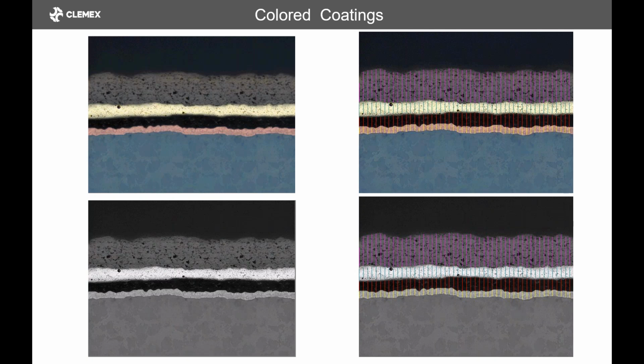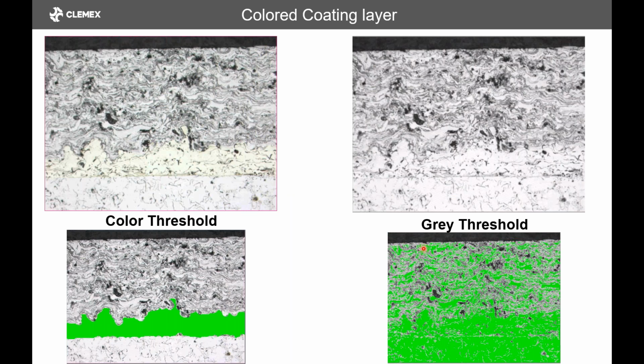Color coding, that's certainly one of the challenges. Now in this case, because the coatings are fairly intense, if we look at it in gray, we can still detect them correctly. But you'll see in the next one, we have a color that is definitely quite weaker. And if we use a regular threshold, this is what we get. We end up with this background being detected. So it doesn't work very well. So by using a color threshold, basically you click on the yellow here until it's full, and then you end up with the proper detection of our coating.